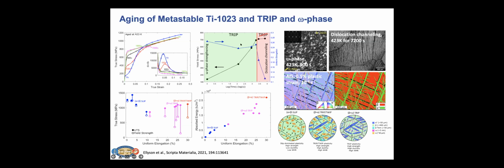And this is due to the combined effect of the omega phase in the microstructure in concert with the transformation-induced plasticity, or TRIP. There is a point at which we overage the microstructure and we end up forming a different mechanism of dislocation channeling that we see. Shown here is some postmortem microscopy where clearly we have transformation of martensite with deformation. And this kind of just summarizes the state of the art in terms of these metastable Ti microstructures that we can generate with different deformation mechanisms that are active.